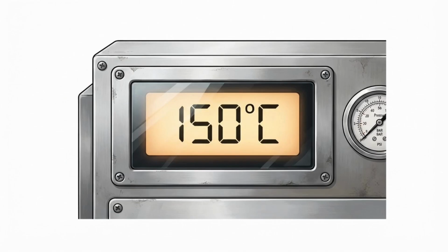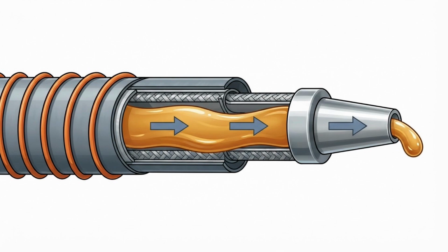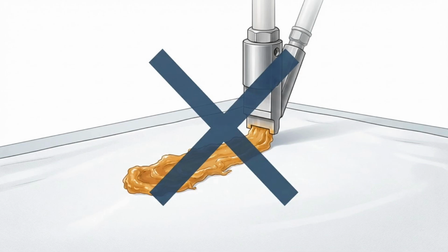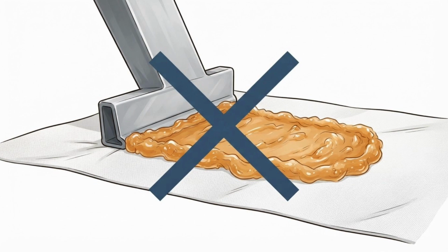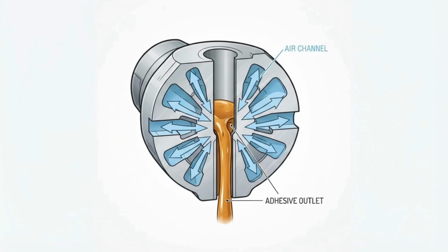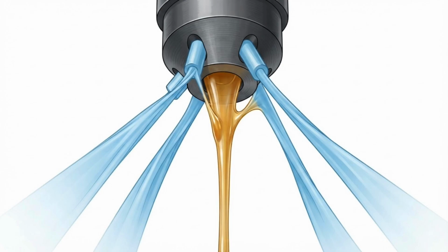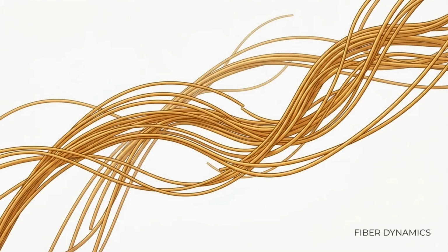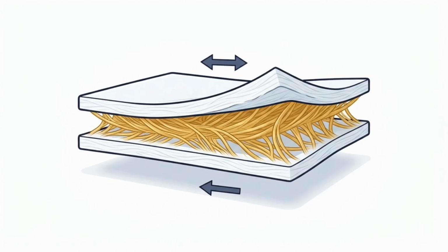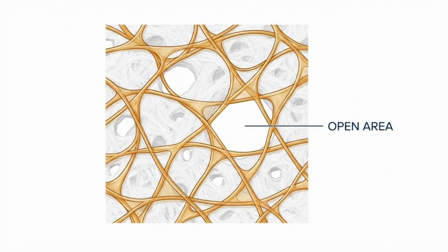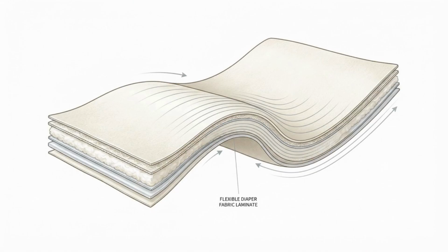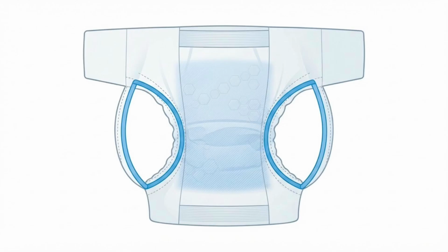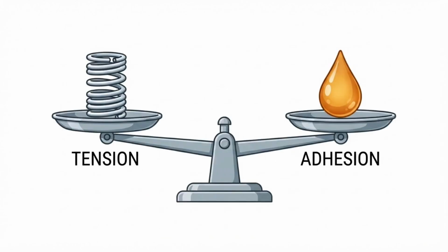Solid blocks of thermoplastic adhesive are melted at over 150 degrees Celsius and pumped through heated hoses to application nozzles. These nozzles do not simply smear the glue onto the fabric. Instead, they use jets of heated compressed air to whip the microscopic streams of liquid adhesive into chaotic, swirling patterns, laying down a spider web-like matrix of glue. This fine web provides immense bonding strength while leaving the vast majority of the fabric surface open and breathable, ensuring the diaper remains soft and flexible.